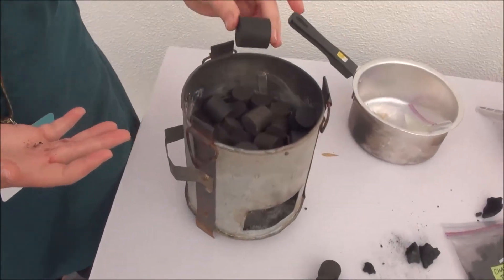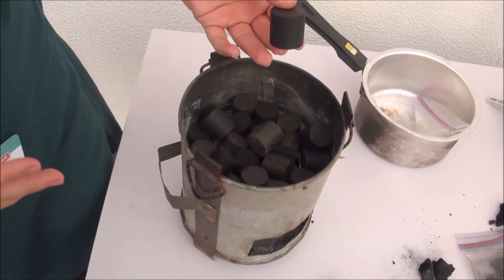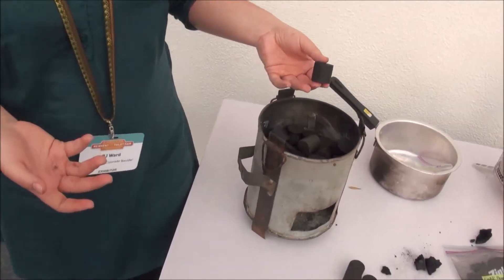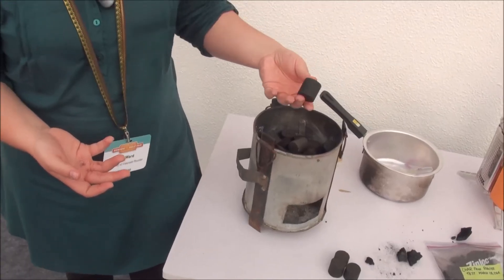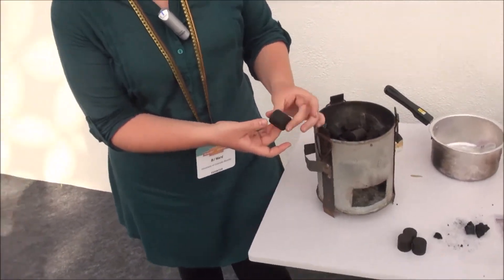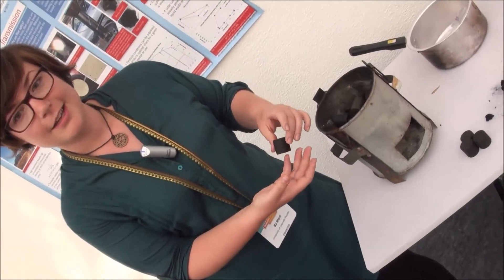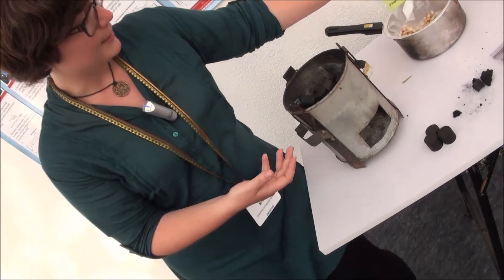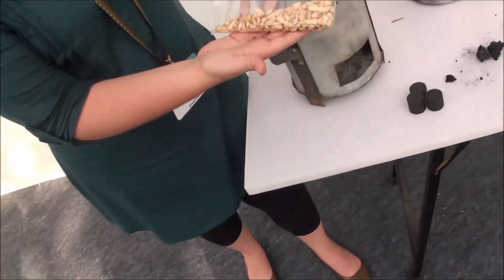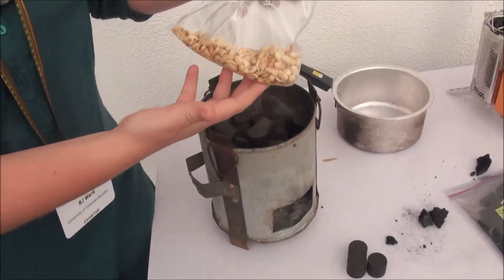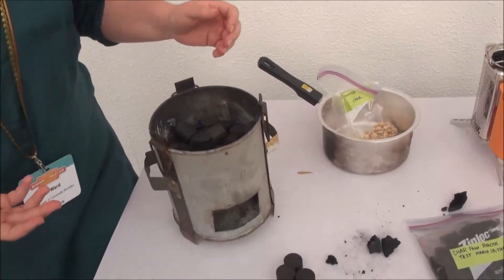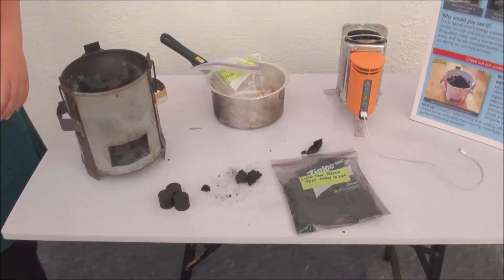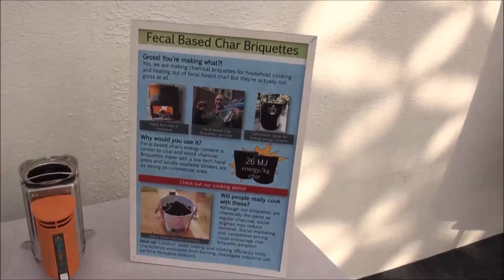We found that it has an energy content similar to regular charcoal briquettes, about 26 megajoules per kilogram, which is considerably high. We've begun testing these briquettes to look at their cooking efficiency in a typical residential cooking scenario. A couple of days ago, we made these roasted peanuts on our charcoal briquette stove, which is pretty great. We're excited about looking into this further and seeing what kind of value this has in the markets where we would be deploying.